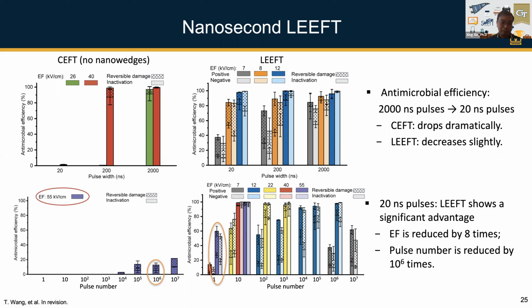Why we feel very excited about this result is that, as I mentioned, the electric field strength is very limited to certain areas, right? So if you want to increase the throughput, you really need very good mixing, and you need to send all your bacteria or microorganisms into these regions. What we can demonstrate here is that if the contact time can be very short, then theoretically our system can still achieve very high throughput, right? As long as during the mixing the bacteria touch the electrodes, they will get killed. That will be great, so they don't need to stay in the regions of strong electric field for a very long time. 20 nanosecond is really short, you can even imagine how short a time that is.